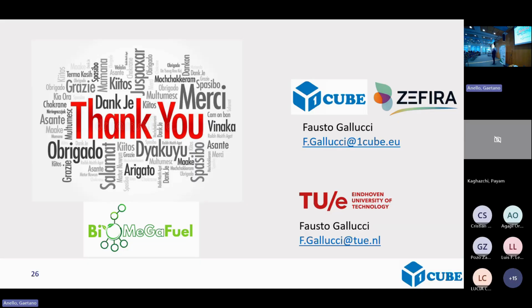We reach selectivities that are not 100%, but we have selectivities of 10, 15, in some cases 40. The latest results of the MEMCAT project show that we can have a selectivity of 40. In that case, of course, some hydrogen may go through, so you have to work a little on the reactor design. But yes, water is smaller than hydrogen. I see very nice discussions popping up during lunch. Let's thank the speaker again.